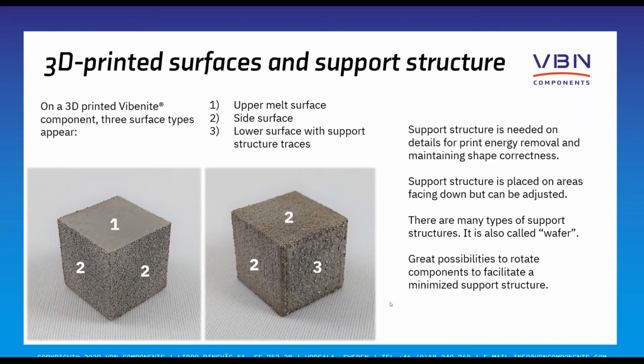To sum up, you can do a lot of things to really minimize the need of the support structure. But typically you need support structure to get good geometrical correctness of your component. If you don't, you get some swelling. We do not have the enormous problem as you typically have in laser printing, since we are using electron beam printing, but we still have the need of removing energy so that the component will stay in shape.